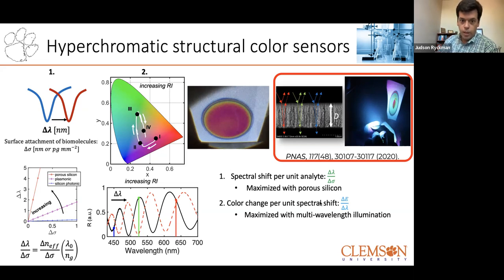So we need both of these. And to obtain the second piece, we found that using multiple laser wavelengths really allows the maximum possible delta E per delta lambda. So that is, if this sensor shifts its spectrum in response to the analytes, the color change is maximized. And what I'm showing here is actual experimental data where we demonstrate this effect.